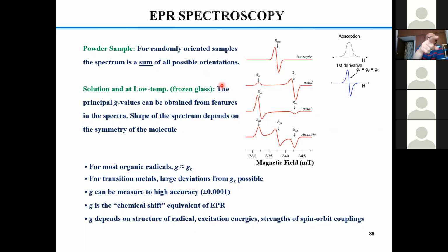But if you take a monodentate ligand, like in the previous cases, nickel hexaaqua, copper hexaaqua, you are likely to have, at least in the solid state, where it cannot distinguish X, Y, and Z too much, a room temperature EPR profile that would look like an isotropic situation, where gx, gy, gz won't be resolved. You will get one absorption, and as a derivative curve, a broad spectrum, one spectrum without any further resolution. Now, if you get this one spectrum, don't be confused with the free radical signal. If you calculate the g value at this point, you could easily distinguish: the g would be much greater than the free radical g value of 2.00 something, at 2.1234 something, and that would tell you, keeping your eyes closed, from the g value that this is certainly metal based.